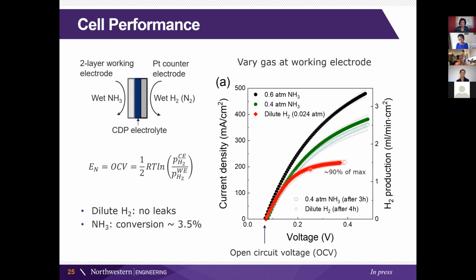That tells us that we're not splitting any of the water that we're supplying here. We wouldn't expect it to at a relatively small voltage. Splitting water is a holy grail, of course, and if we were doing it at such a low voltage, that would be great, but we're not. We're just, in this case, breaking up the hydrogen and pumping it out on the other side.